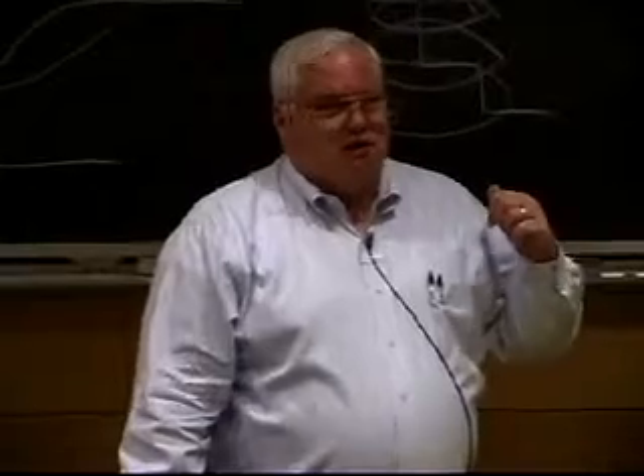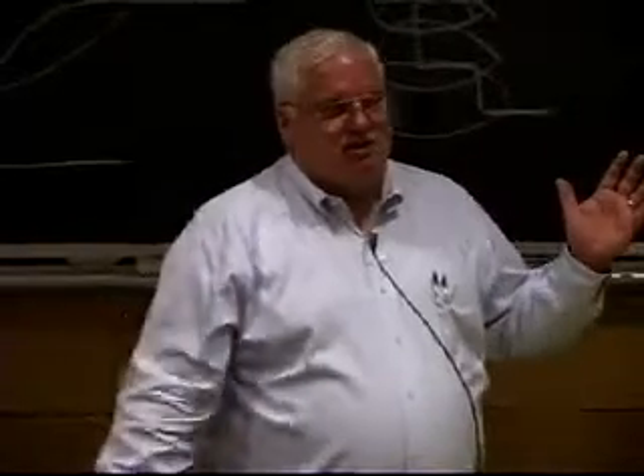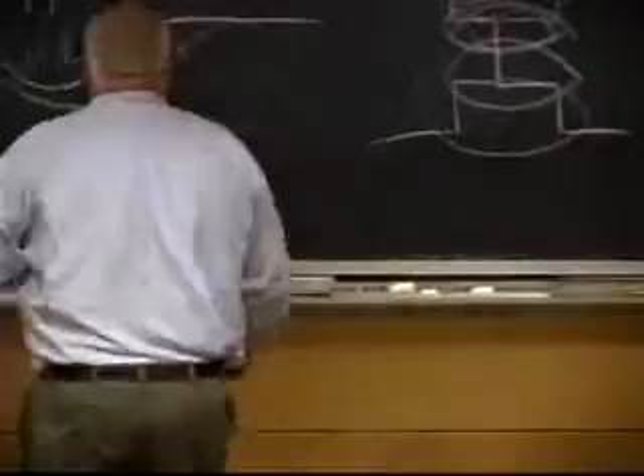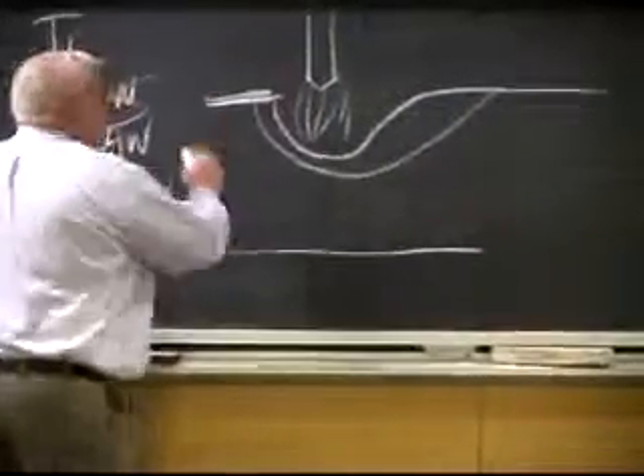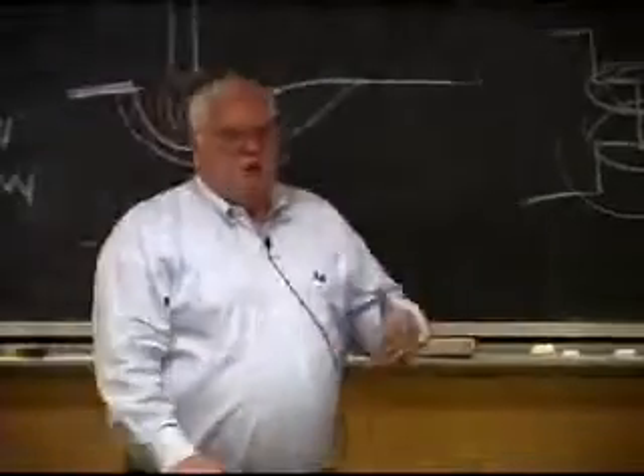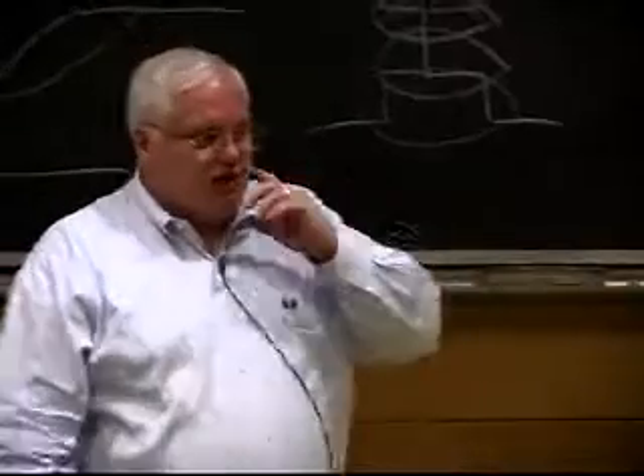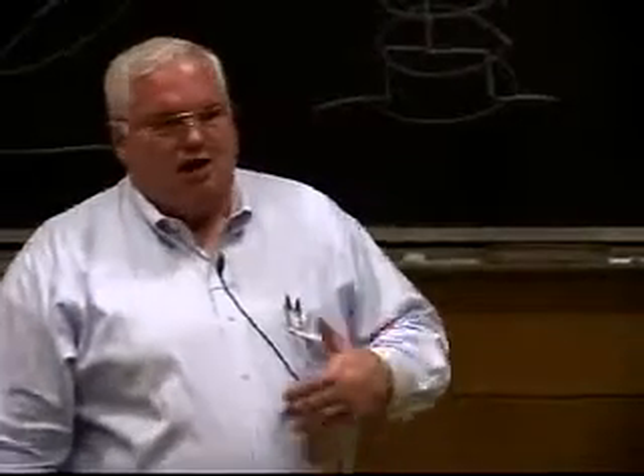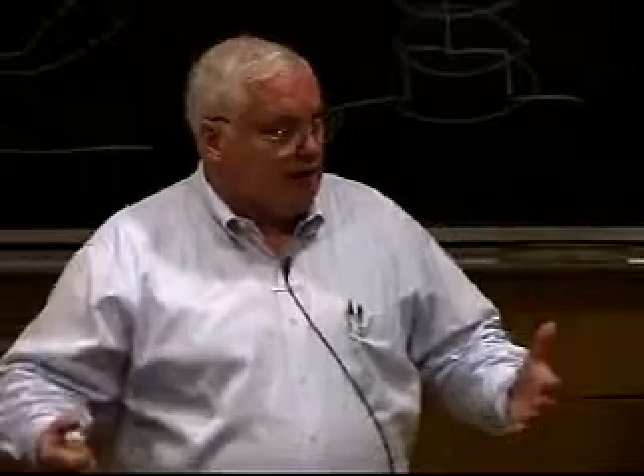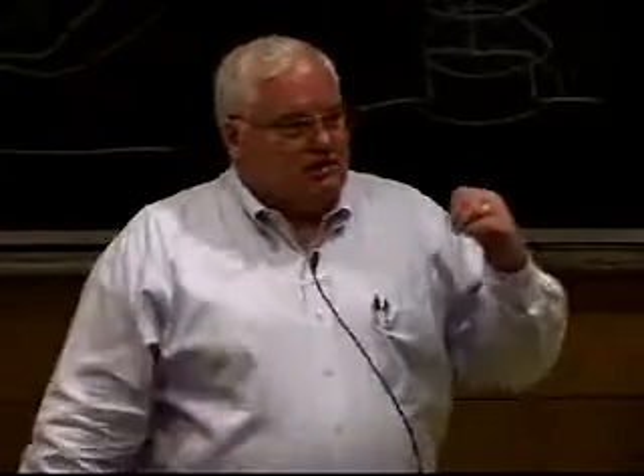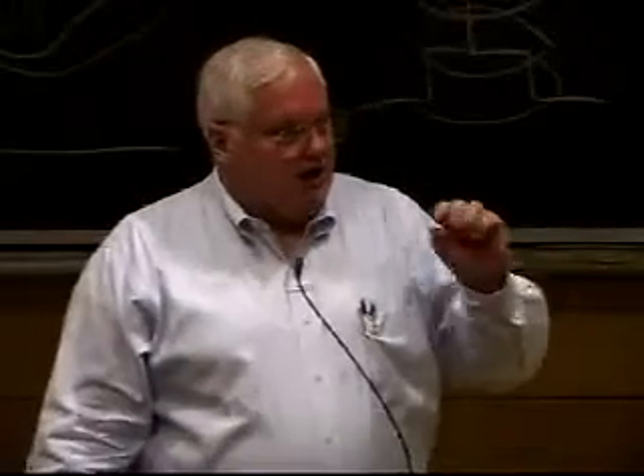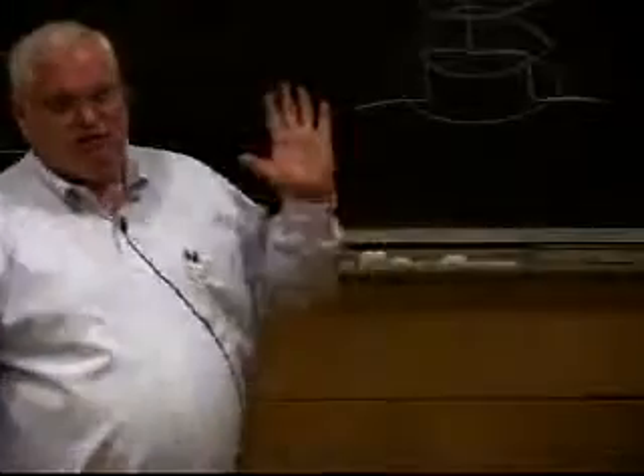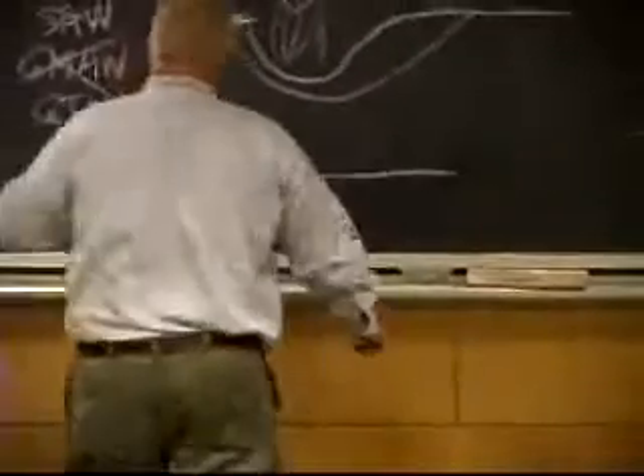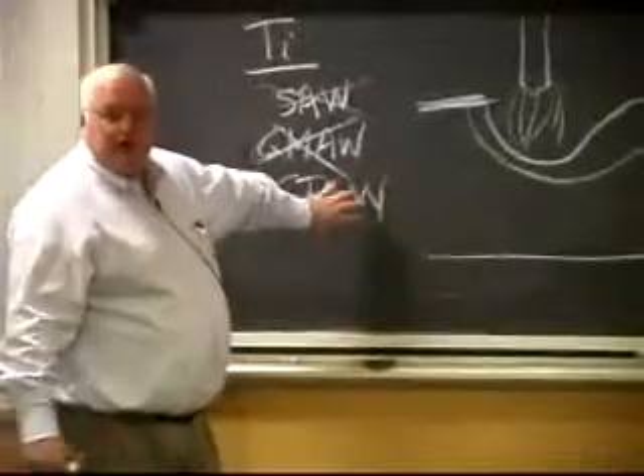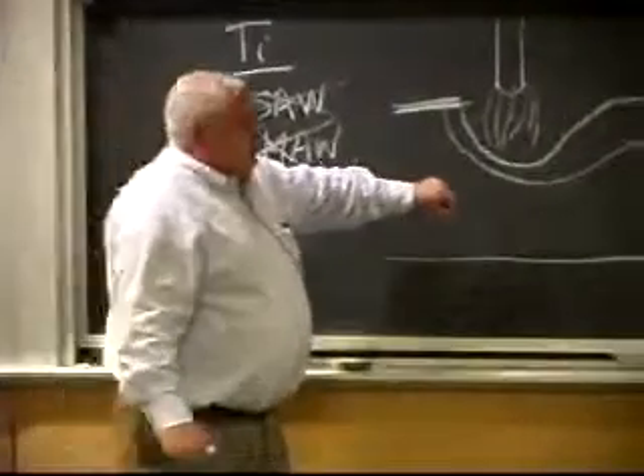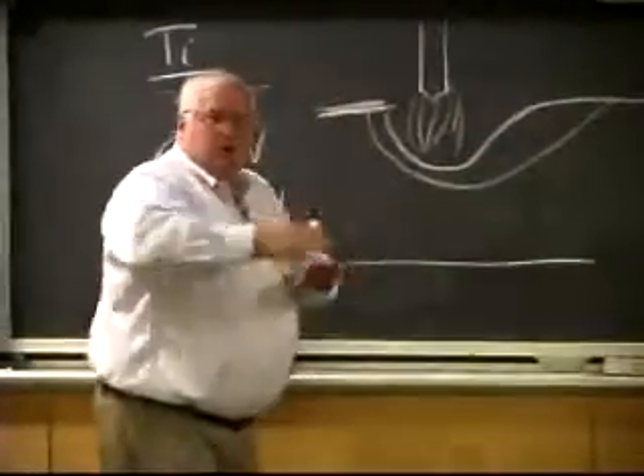More productive than submerged arc welding, and no flux involved. Actually, there was a small flux. You'd paint on this little coating of some of these specialized chlorides and fluorides. Well, what happened in 1985, when peace started breaking out, and the Soviets were looking for foreign exchange, the Paton Institute started trying to market some of their technology abroad, and they started selling this flux. If you want to get the Soviet flux for titanium for this gas tungsten arc process, it's not submerged arc, and the flux still can be very expensive, except it's made in the Soviet Union, so it's not $100 a kilo. But it's still 10 or 20 bucks a pound, but you're just putting a little whitewash on.